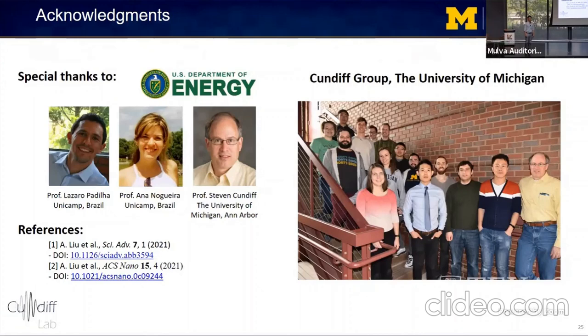Yes. Okay. Thank you. It's a beautiful talk, and it's always a pleasure to see Steve's work, and you've done great work here. There's something that you might be familiar with, and the audience might not be, because you've looked at perovskites. You're looking at the temperature dependence. At 4 Kelvin, the system is not in the same state that it's in at 300 Kelvin, because at 300 Kelvin, it's glassy and disordered. And at 4 Kelvin, you freeze out that disorder.